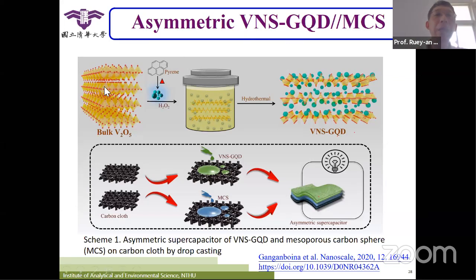Not just for halloysite nanotube, you can still immobilize the GQD on the surface of two-dimensional materials. For example, VNS here, vanadium oxide nanosheet. Here is the bulk V2O5. We try to use the hydrothermal method to separate the bulk V2O5 into single layers. And then we put the GQDs on the surface of our VNS, so that's what we call the VNS-GQD. Here we do not use citric acid or some sugar. We use pyrene. The pyrene will be quite easy to form GQD and their surface will be relatively high.